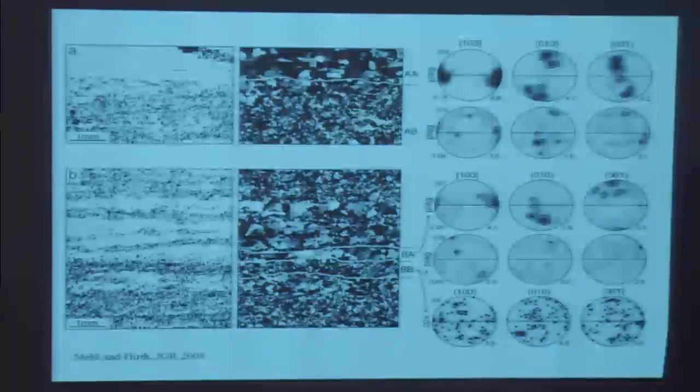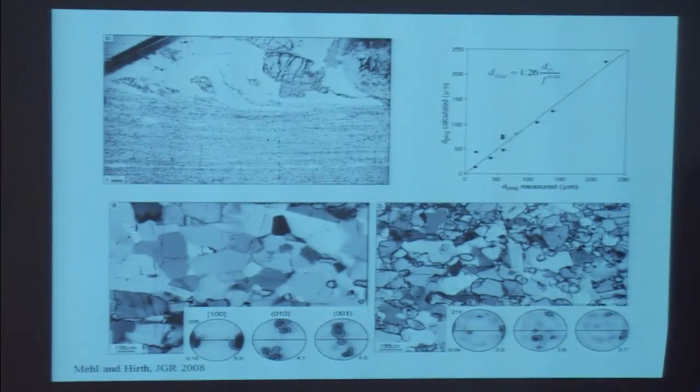There's also, and this is really important for evolution of rheology, the question of what is the role of the second phases on viscosity? So what I just showed you is that the rock was fine-grained where there were two phases together. So what's happening is, if you mix the phases, the grains might want to grow, so thermodynamically they might want to grow to be larger, but they're stuck because there's someone in the way. You might hear the vernacular, Zener pinning, is a word for that. And Zener pinning has a nice formula, and basically what it says is if you have more of a second phase and that second phase is smaller, the grain size is pinned to be a smaller value.